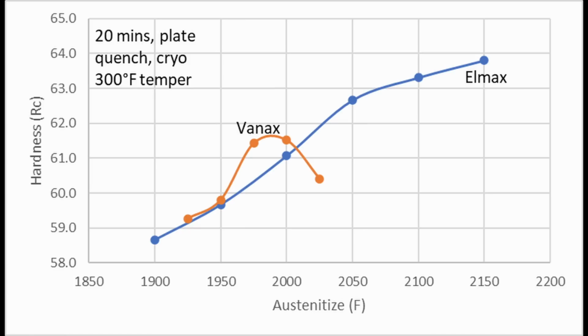Also, the composition of steel can be slightly different from batch to batch as you receive it from the steel company. And the austenitizing temperature where the peak hardness is will vary with the composition. Also, there's variation in temperature within the furnace and between furnace batches, which means it's usually better to go a little bit conservative. So we wouldn't want to do 2000 degrees austenitizing because we might overshoot in the furnace, or a batch of the Vanax may be on the rich side, which would shift the austenitizing hardness curve down.